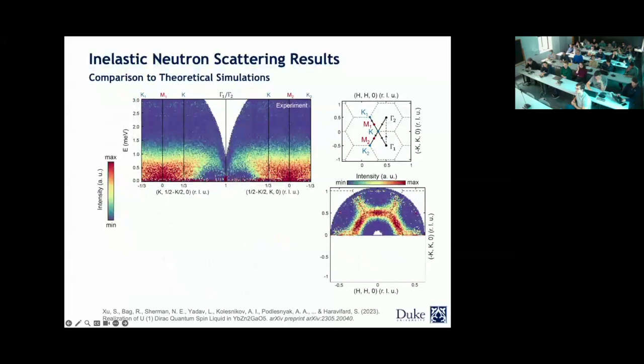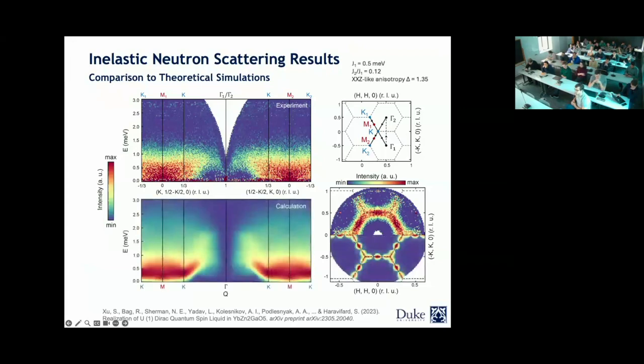So here is the energy as a function of Q for the experimental data. So you're looking at these excitations. There is basically a gap that starts opening as we get close to the gamma point, which is also important. And here I'm just showing you the path along which we collected the data. And here's a cut at low energies. It's not very low energy. It's integrated over everything from 0.5 meV down. And here is the theoretical model based on this delta value that was done for the same compound.